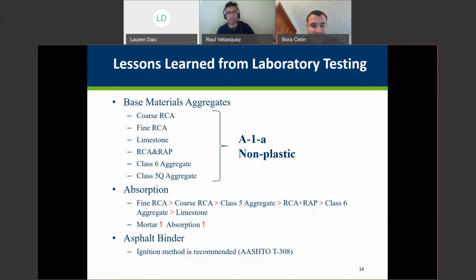Having a good absorption may have some advantages in that it absorbs water, which starts rehydration of some of the remaining cement in the RCA materials, recycled aggregate materials, and increases stiffness, or yields higher stiffness values. However, too much absorption may keep too much moisture in the material, and eventually in the long term may cause some performance issues. So it needs to be balanced properly.